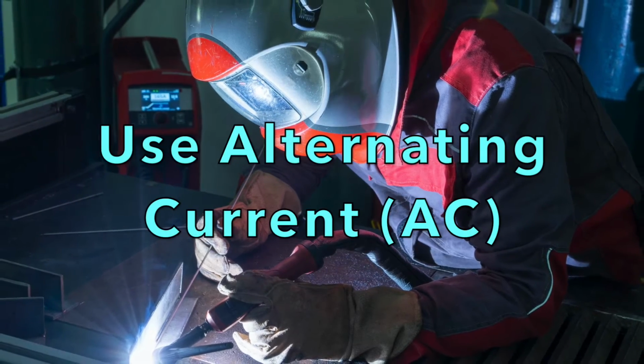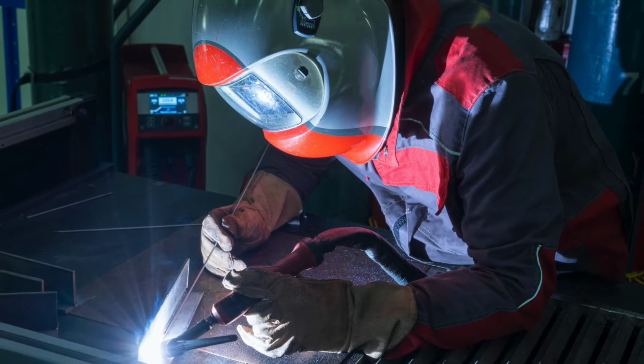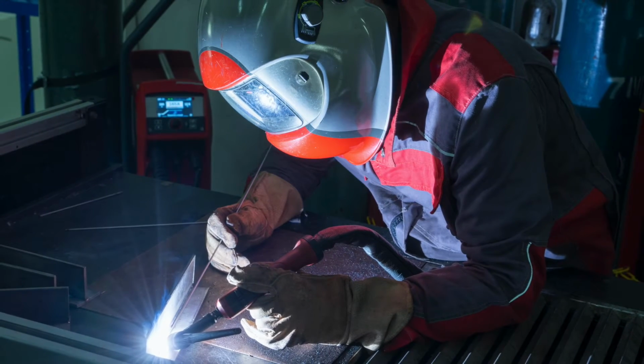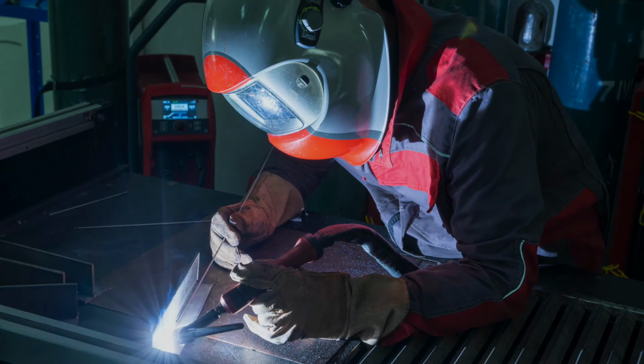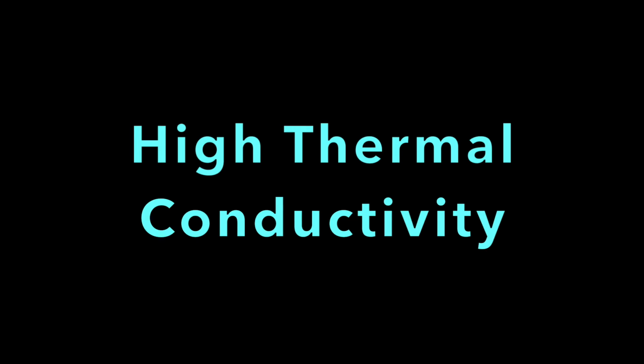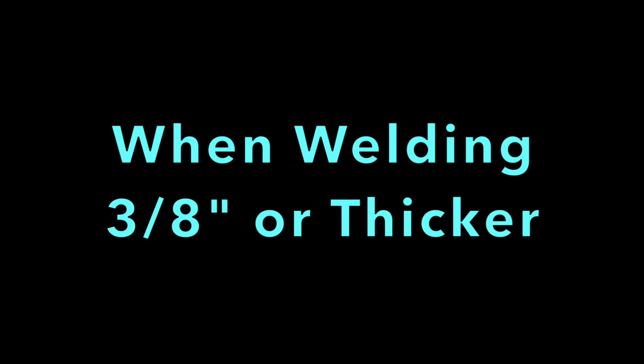Alternating current should be used when welding on aluminum. The alternating current provides medium penetration and great cleaning action. Aluminum has a very high thermal conductivity and disperses heat quickly. It is recommended to preheat aluminum to 300 degrees Fahrenheit when welding on material thicker than 3/8 of an inch.